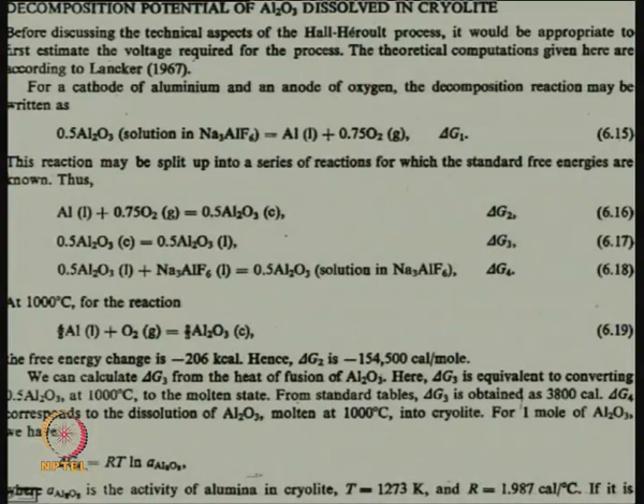Now, this is how we calculate. We want to know the decomposition of alumina into aluminum and oxygen, and this alumina is in solution. It is 0.5 Al2O3 giving aluminum plus 0.75 O2. I am writing it in this form so that we are always getting one atom of aluminum. Suppose the free energy change for this is delta G1.